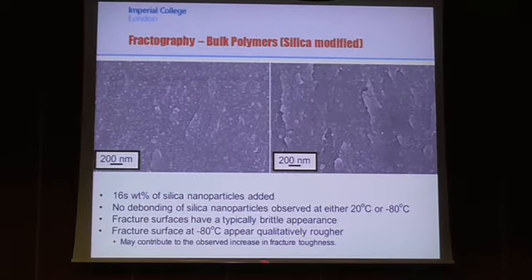We move on to the silica modified materials. With 16 weight% on both sides, at room temperature and at low temperature, we see that there's no debonding of silica nanoparticles in either image. The fracture surfaces have a typically brittle appearance. These fracture surfaces appear a little bit rougher, so obviously a rougher surface is an increased fracture area. This may contribute to our observed increase in fracture toughness from earlier on. But just summing up the area contribution, like in the Faber and Evans paper, doesn't account for everything.